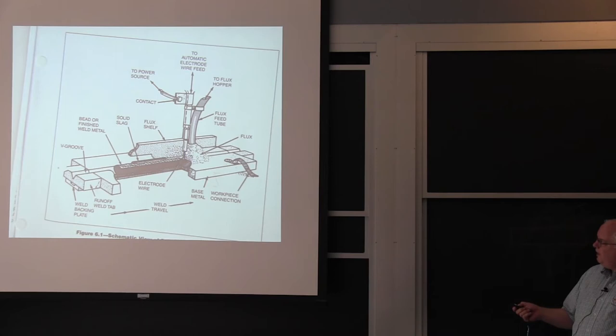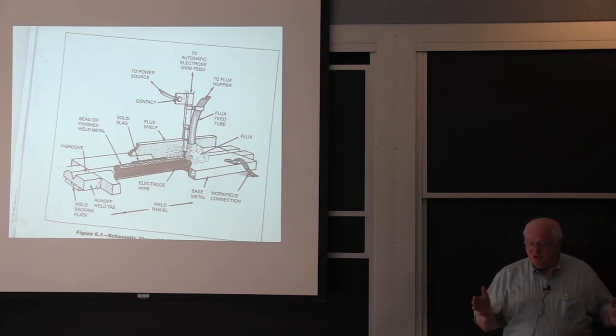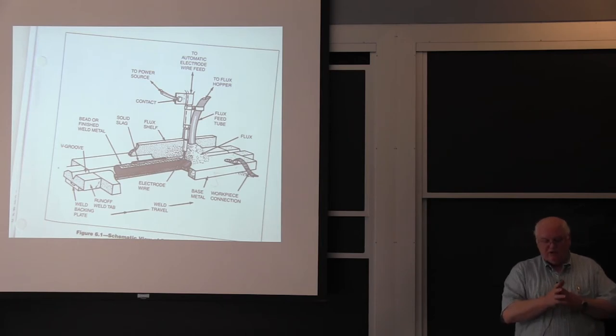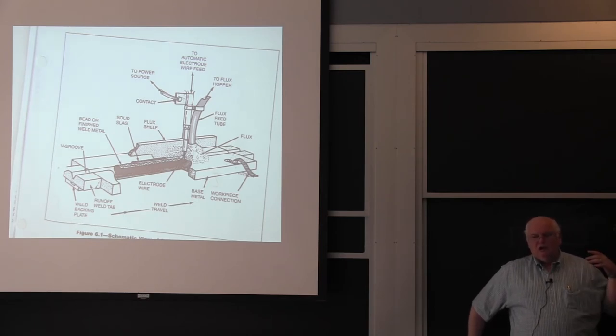There's a patent on it and the process is still used widely for steel. There's a letter from Franklin Roosevelt to Winston Churchill in 1943 talking about this wonderful new welding process that was helping build ships. This is the process. It was invented by Union Carbide and that's why it was called Union Melt. It turns out you can weld titanium by this process. This was my first research contract as a young professor. Turns out Union Carbide, before it changed its name to Praxair and other things because of the Bhopal disaster, had taken a contract from the Navy to do submerged arc welding of titanium. That was in the mid-70s. The Navy was still interested in trying to weld heavy section titanium. But you had to keep the oxygen and nitrogen low in order to get good toughness in your welds.